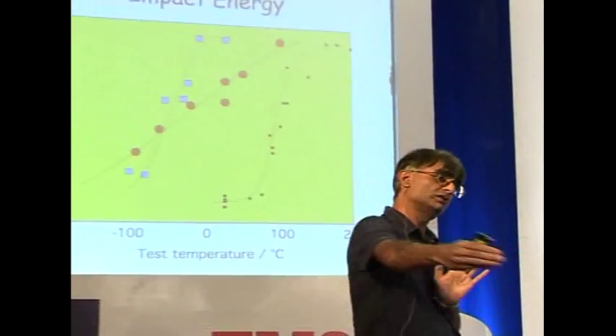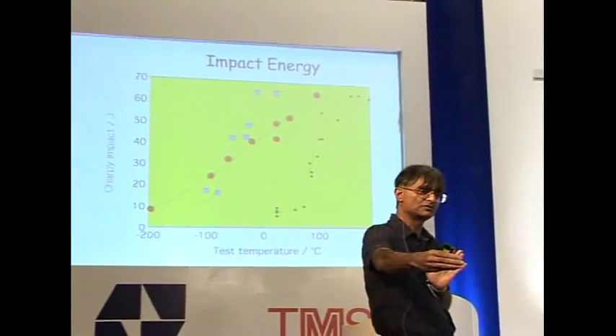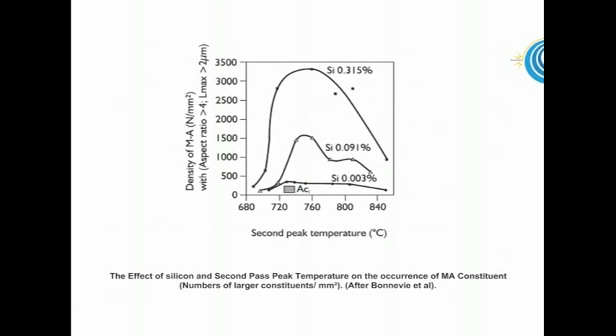Although claims have been made in the literature suggesting that niobium may promote increased levels of MA, this contention is not supported by either Professor Bhadeshia or Dr. Kirkwood's studies. Dr. Kirkwood concludes that if this is an area of concern, the simplest solution is to reduce carbon and silicon as in the HTP steels. This approach reduces MA to the lowest possible levels.